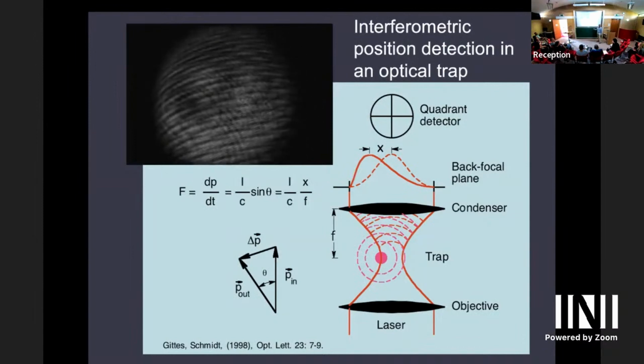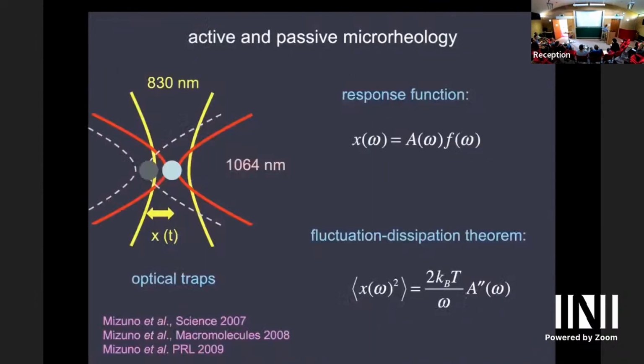and that's nothing other than momentum transfer. The photons transfer momentum to the bead, and then of course there's a reaction force on the photon. So if the bead is over to the left, the light gets pushed to the left here, and the bead gets pulled back into the center by that momentum transfer. That is useful because you can then use this non-imaging. This is just imaging the back focal plane, but you can project the back focal plane onto the quadrant diode, and then with high temporal resolution, track the relative displacement of these particles in that optical trap. So that was a critical technical issue to get high bandwidth rheology out of this.